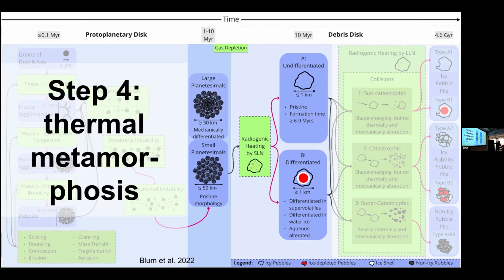And these short-lived nuclei decay, and with a decay, they deposit heat. So they deposit heat into a body that consists, if it's a small body, of pebbles, which themselves consist of very tiny dust particles. So the thermal conductivity within a pebble is low, but the thermal conductivity of the whole pebble pile is even lower. So we have an extremely bad thermal conductivity, and the heat generated in the center is stuck there. And that can lead to the evaporation of ices, to the migration of ices, for larger planetesimals, even to the melting and the differentiation.